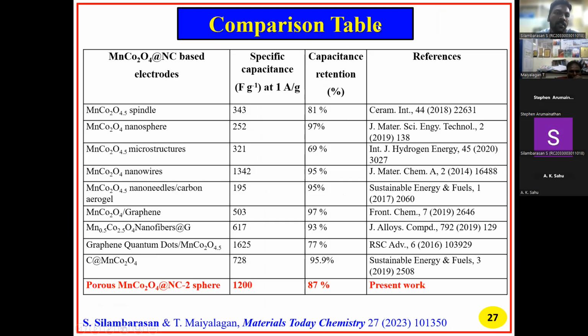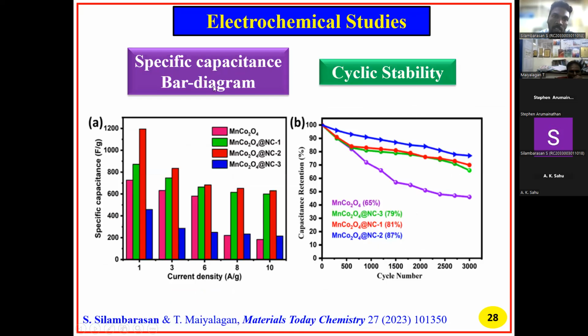Next, the comparison table. Compared to previous literature, our MnCo2O4 material is confirmed here: specific capacitance at 1 amp of 1200, with retention of 87%. Next, the specific capacitance bar diagram in figure A, current density versus specific capacitance, is shown here. Then the cyclic stability: we took 3000 cycles. Compared to the others, sample 2 has the higher retention percentage, around 87%.